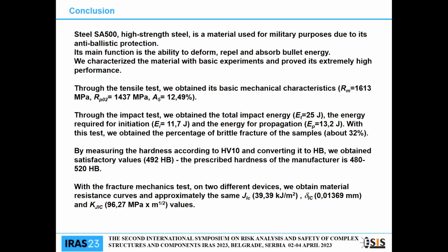So here we stop now with the testing of this steel. We are satisfied with the results we got on the tensile test. Also, the impact Charpy test, the instrumented Charpy test, also shows that we have higher energy for propagation than energy for initiation. This is good for this type of construction. And at the end, we can see that our KJIC factor is more than 96, and we hoped to get 85.